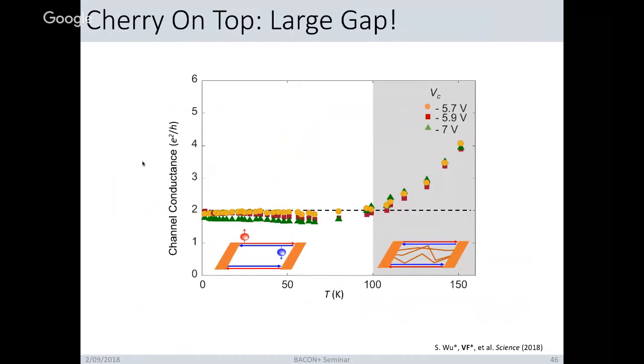One other topic is that the insulating phase appears to persist to high temperature. Or more precisely stated, in our measurement, we can see that the channel conductance corresponding to this 2e square over h given by the two helical edge modes on either side of the sample persists up to nearly 100 Kelvin. And above this temperature scale, we see that the channel conductance starts to increase, indicative of thermally-activated bulk channels that tells us that these edge modes are really dominating the system for quite a large temperature range over an order of magnitude higher than is seen in the other semiconductor heterostructures. And this feature has a lot of potential for utility in the future because now we can actually operate at much higher temperatures. Maybe for some optical studies, it's kind of hard to operate at extremely low temperatures, but this range is much easier. So there's some potential there. So we're very excited to see this data pop out as well.